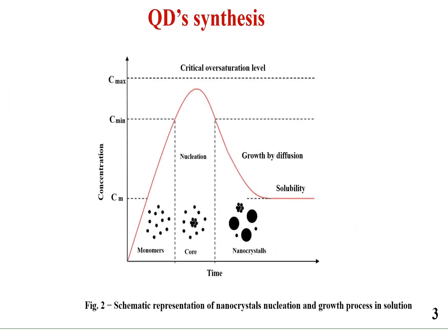Currently, all methods of quantum dot synthesis may be divided into physical and chemical. Physical synthesis methods need expensive equipment, so chemical methods are the most promising. The general concept of quantum dot chemical synthesis consists in obtaining an ion source of the semiconductor material composing the core of the particle, with the addition of surfactant stabilizers that passivate the surface of the particle and prevent aggregation, and the build-up of semiconductor shells in order to reduce the effect of quantum dot structure defects on their properties.